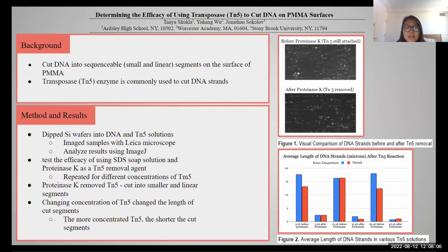The results show that changing TN5 concentration does change the length of the DNA strands that are cut. The more concentrated TN5 is, the shorter the strands will be. As shown in figure 2, we are able to produce an average of 2 to 3 microns long cut DNA strands using 5 microliters of TN5 solution. When we used 20 microliters of TN5 solution, we ended up with an average of 0.5 micron long cut DNA strands. We want to give special thanks to Dr. Sokolov and Dr. Rafalovich for helping us do this project. Thank you.